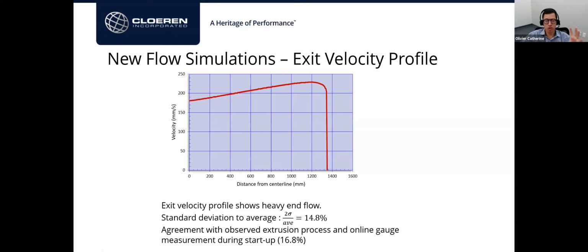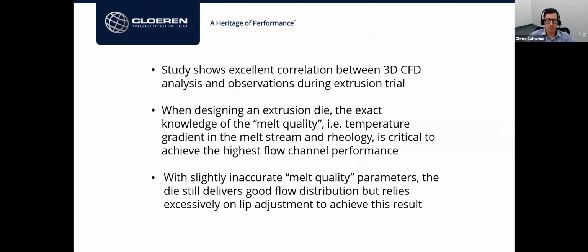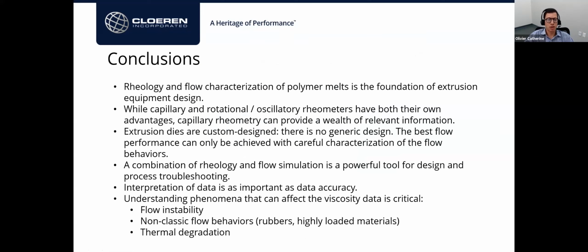So from there, we have a good, solid data point, and we can go back and correct the die flow channel for their process, or see if there's any adjustment they can do on their extrusion process to minimize the shear heating and also avoid that temperature mismatch that they were trying to cool the melt from. So in conclusion, I think I've shown today that rheology and flow characterization of polymer melts is a very important piece of extrusion equipment design and troubleshooting.